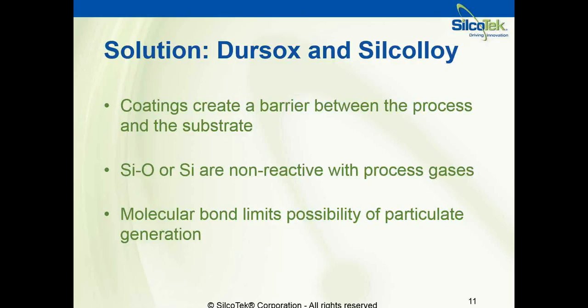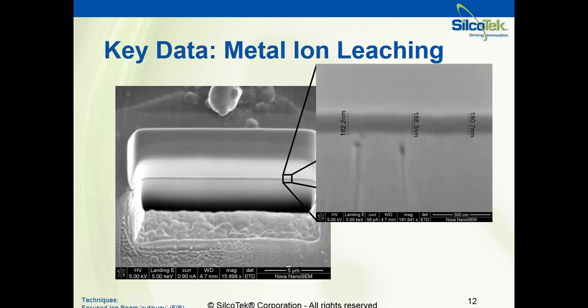SiO, which is the Dursox, or simply Si silicon, the Silcolloy coating, are non-reactive naturally with the process gases that are commonly used, even for gases that are used to etch silicon oxide or silicon coatings themselves. And of course, the molecular bond of the CVD process greatly limits the possibility of generating particulate that would then be introduced to the process stream and cause problems later on.